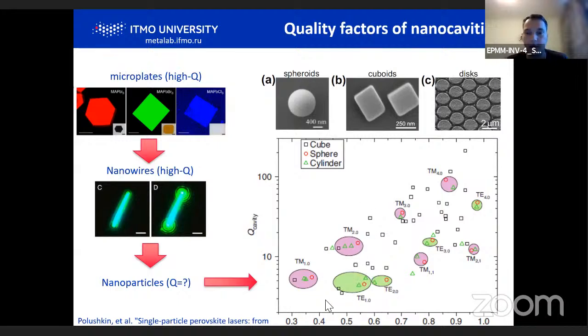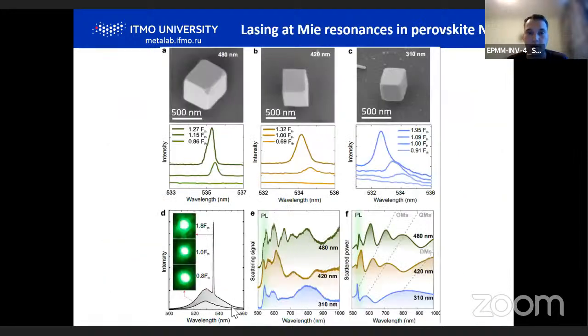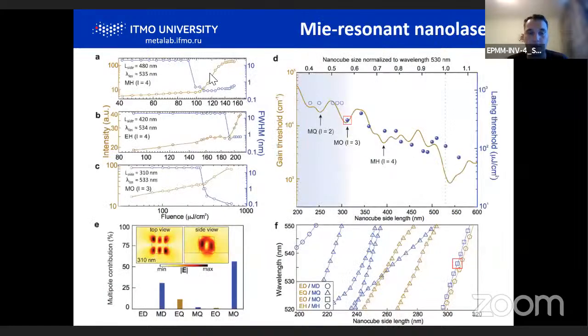And we provided calculations for different shapes of nanoparticles, and we observed that for sub-wavelength particles less than one wavelength, the Q factors are between maybe 10 and 100. So we should work somewhere in this range. And we fabricated such nanoparticles and then tested their lasing properties. We observed a threshold-like appearance of narrow peaks in the visible range, and we also observe Mie resonances in scattering. Also, after characterization of different nanoparticles, we observed different levels of threshold for each nanoparticle.